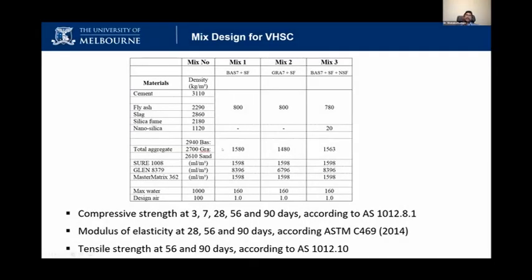This is the mix that we came up with. You can see it's a blended mix. We use the cement, fly ash, slag, silica fume, and nanosilica as well, only for one mix. The binder content is 800, but we use only around 500 kilograms of cement. Around 40% is supplementary cementitious material and only 60% is cement. That helps us reduce the cost as well as the emission, because fly ash, slag and silica fume are byproducts from the coal, steel, and electronic industry.